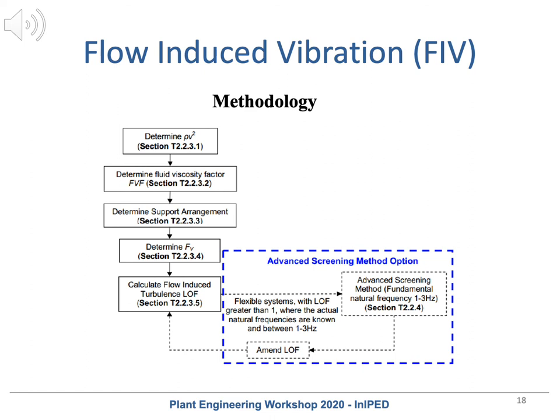For the lines where the second stage is insufficient, there is an alternative method, as long as the supported configuration is flexible and the natural frequency of the system is between 1 and 3 Hz. In this case, the probability of failure is calculated in the same way but with a vibration factor that is calculated according to the equation shown from the Energy Institute.